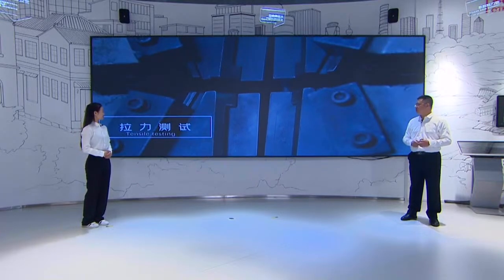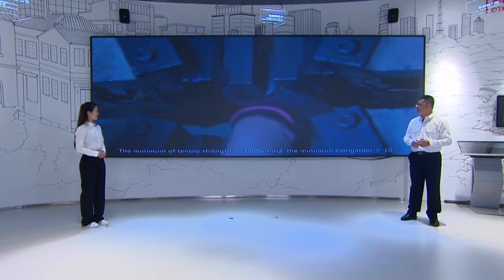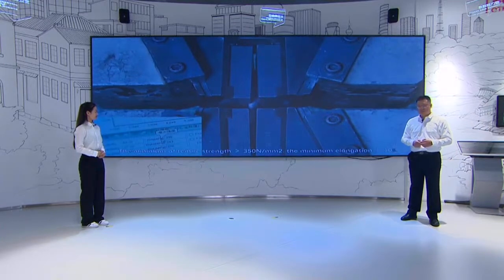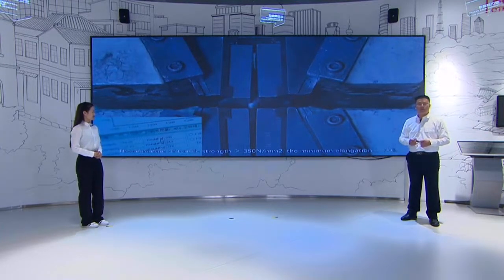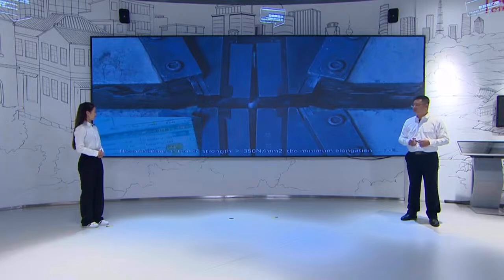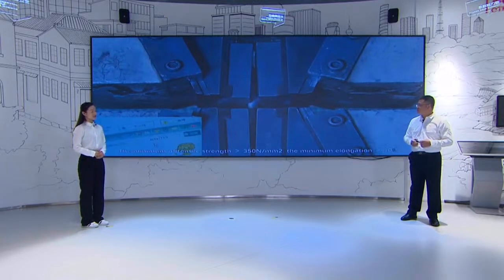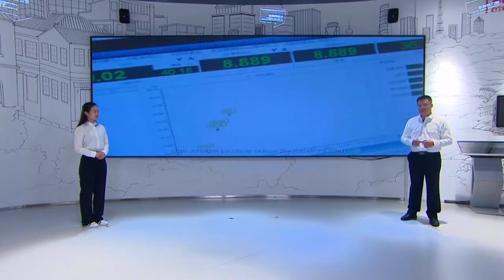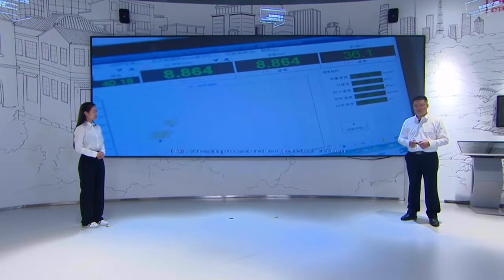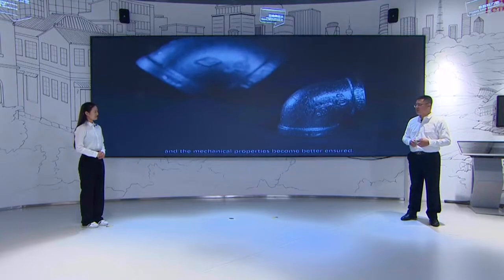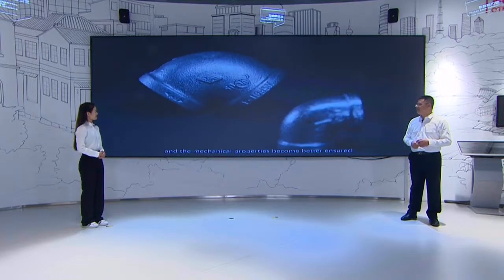6. Tensile testing. The minimum tensile strength greater than or equal to 350 Newton per square millimeter. The minimum elongation greater than or equal to 10%. High-strength products reduce the risk of cracking and the mechanical properties become better ensured.